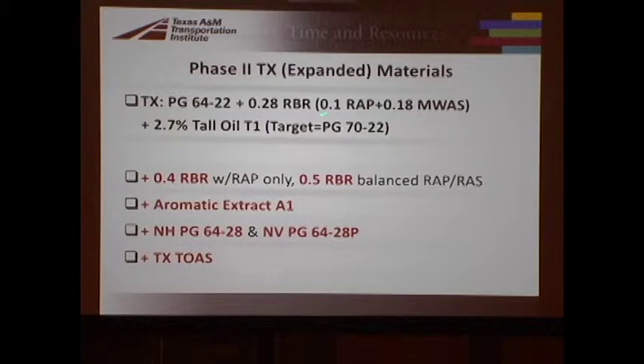We have 0.1 RAP binder ratio and 0.18 RAS binder ratio, and it was manufactured waste type of asphalt shingles. That's important to note. And really, we shouldn't combine this and say, oh yeah, it's 0.3 RBR. It's really important how much of that is RAP and how much of it is RAS. So we always show both now. We also added in a tall oil, which is kind of the new greener types of recycling agents.